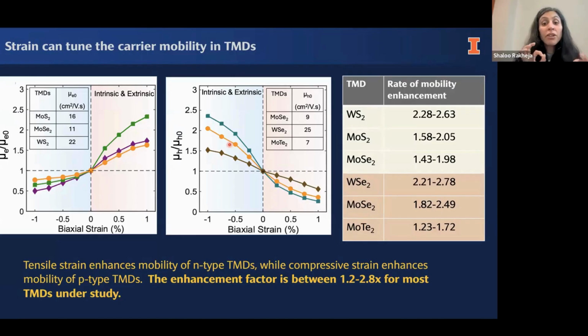And generally, it is very, very robust. We can see that the rate of mobility enhancement can be anywhere from 1.2 to 2.8x for most of the TMDs that we've studied in our research group.